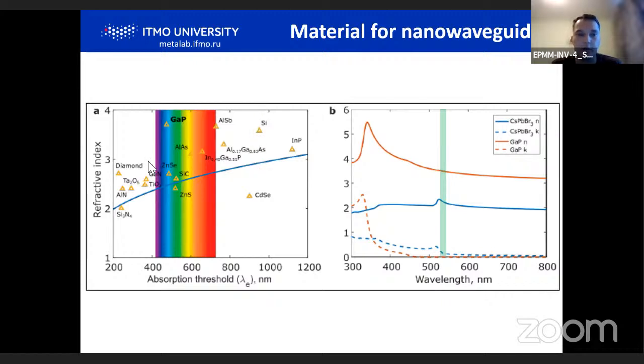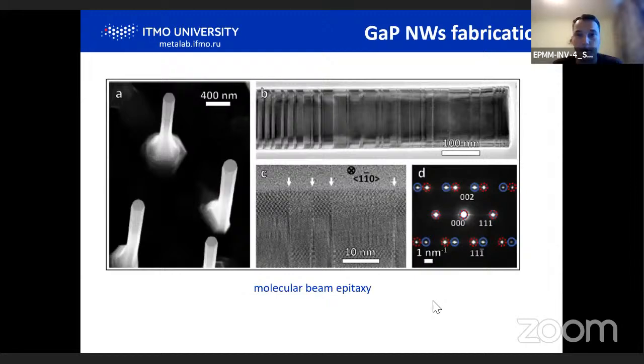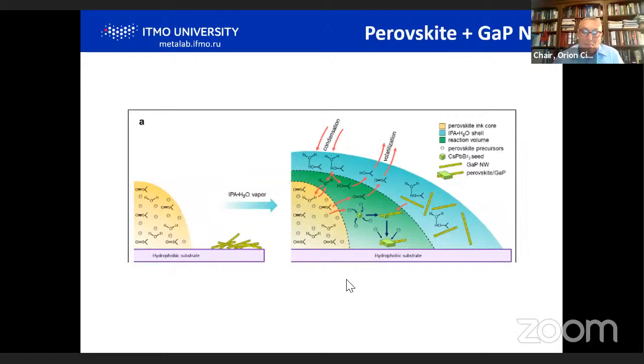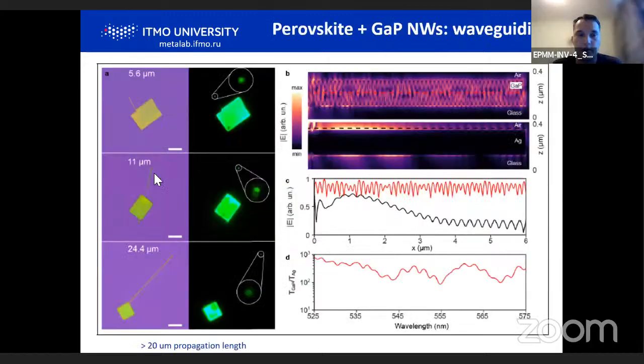So according to the best of our knowledge, gallium phosphide is one of the best materials for this spectral range for green light. You see here the dispersion for this material, and it has very high refractive index and very low losses, just above 500 nanometers. So we fabricated gallium phosphide nanowires, and then... Yes, thanks. And fabricated such micro lasers with integrated nanowires.